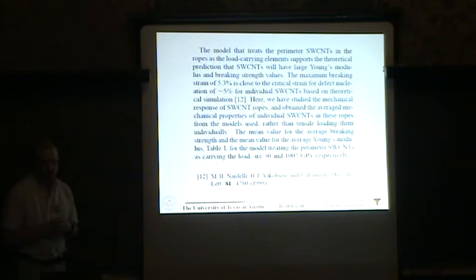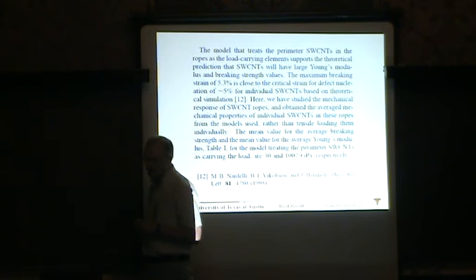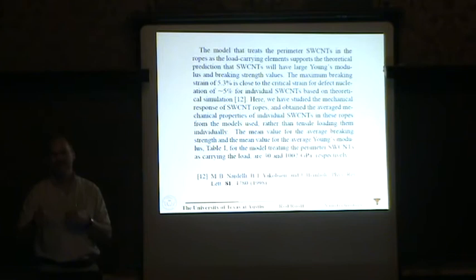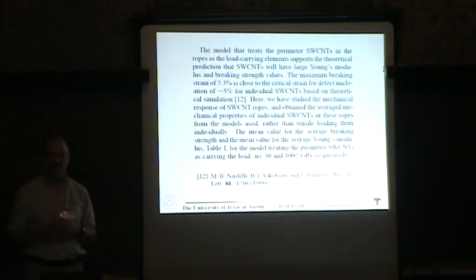So as I mentioned, we did end up measuring strains of order 5%. So one way of explaining lower values than 130 is a model from Boris Yakobson, the Stone-Wales reorganization where you have two neighboring hexagons and one of the bonds will rotate. And you will nucleate a 5-7 defect pair. That's one possible rationalization for measurements at room temperature giving lower values of strength. In other words, you're actually triggering nucleation of defects that can then run through the material, through the nanotube, collide with each other, and build larger defects such as octagons and nonagons. And eventually you have a strong stress concentrator that lowers the observed apparent strength.